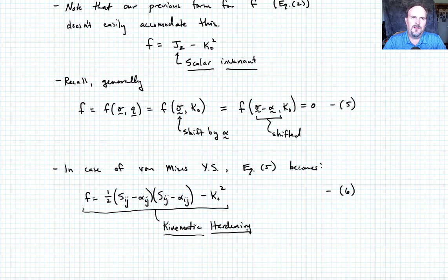So now if you're like me, you're thinking, well, that sounds great, but in the isotropic case, I had a single constant, a single scalar quantity I had to compute, and I think I understood how I would do that with respect to, let's say, a uniaxial stress strain curve. Now I'm looking at this and I'm seeing, well, even if we assume that alpha is symmetric, I see at least maybe 6 quantities I have to evolve in order to capture kinematic hardening.